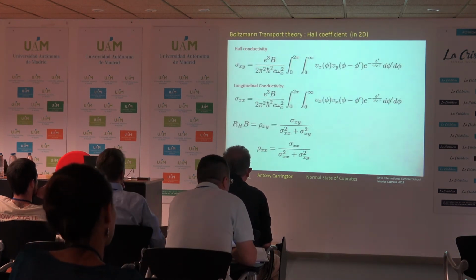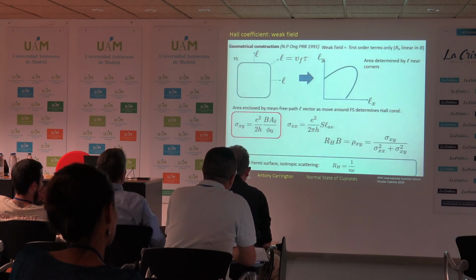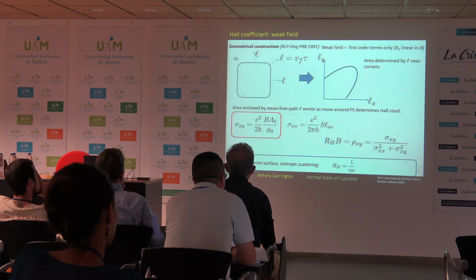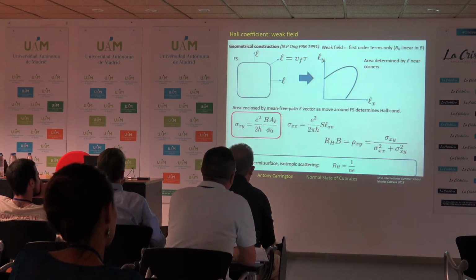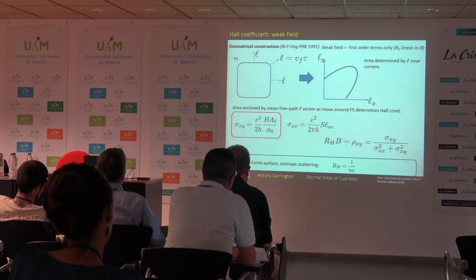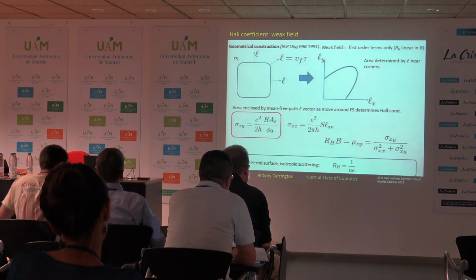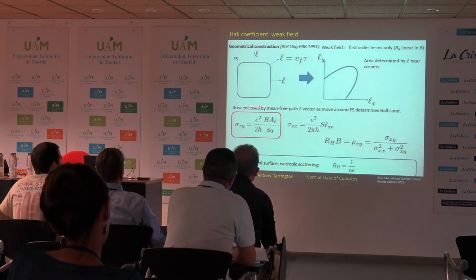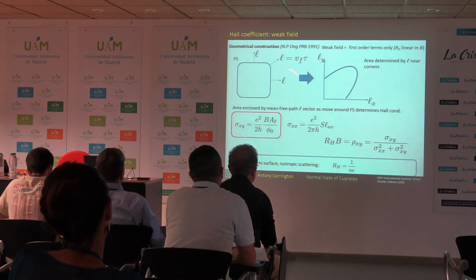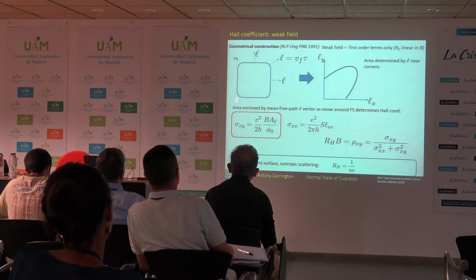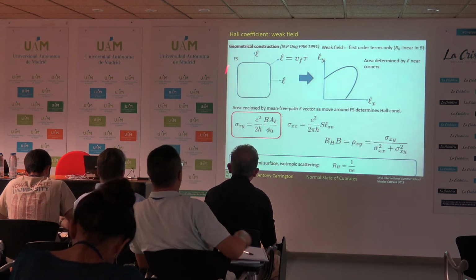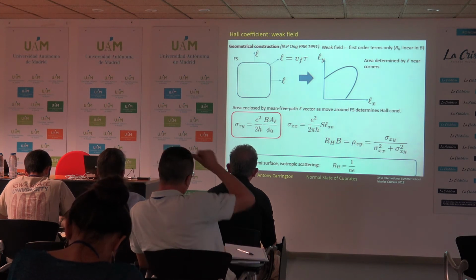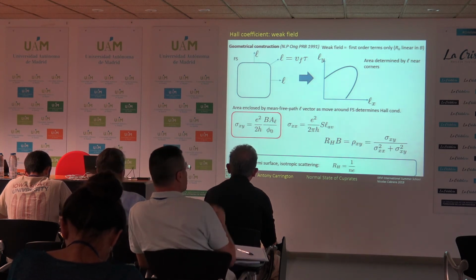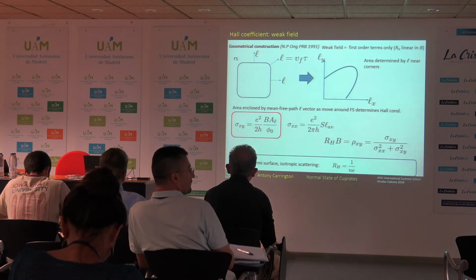Okay, so that's how you do things in general, but in fact, Ong showed back in 1991 a very nice geometrical interpretation of the weak field Hall coefficient. So this is the Hall coefficient in the limit that the field tends to 0. Okay, so the construction that he used was this, that if you take a Fermi surface and just take for the sake of an example, one that's kind of square but with rounded corners, which by coincidence looks a little bit like cuprates, but it serves as an illustration anyway.